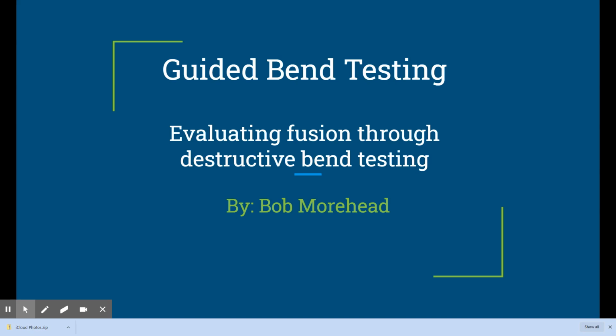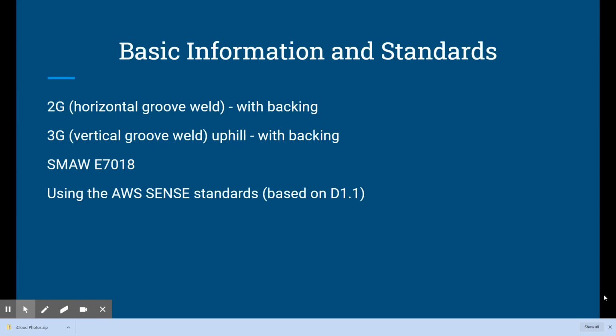So let's start with that. The two welds that we do this on in my classes are a 2G, or a horizontal groove weld with a backing strip, and a 3G, which would be a vertical groove weld with an uphill progression, also with a backing strip. We do this with the SMAW or stick welding process with a 7018 electrode. Our standard that we test to is the AWS, American Welding Society SENSE program standard. And that is pretty much identical to the D1.1 structural welding code. So if you're familiar with that, it's going to look the same.